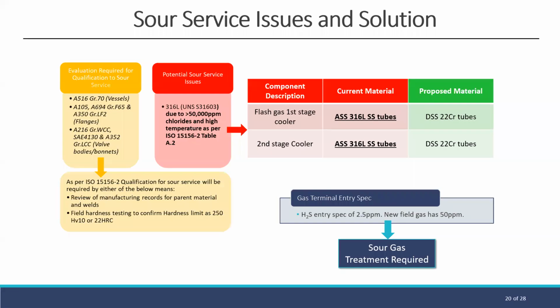So with the introduction of the new slightly sour well, we needed to assess what the H2S effect would be on topsides. What we've done for this is use ISO 15156 to essentially qualify the materials we have in topsides. Generally, we have compliance there, but there are a number of carbon steel products that require further qualification, but we don't foresee this to have any real issue.